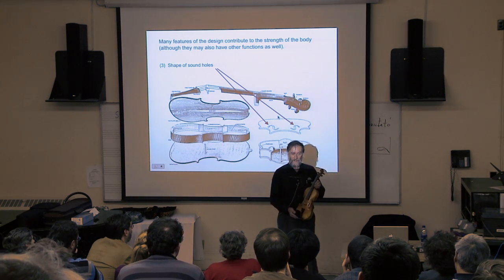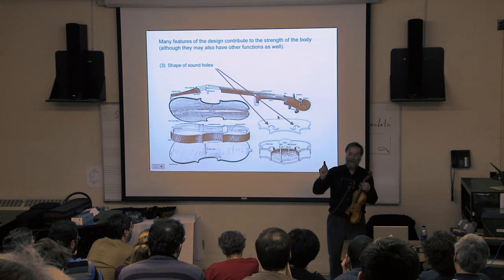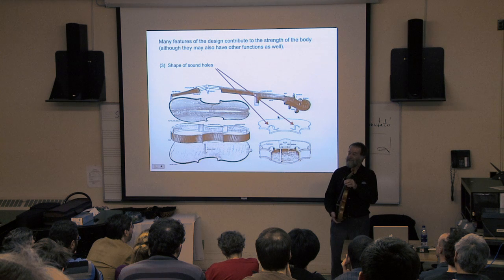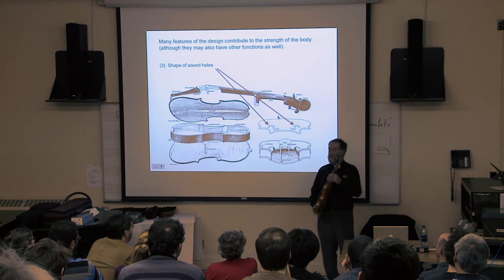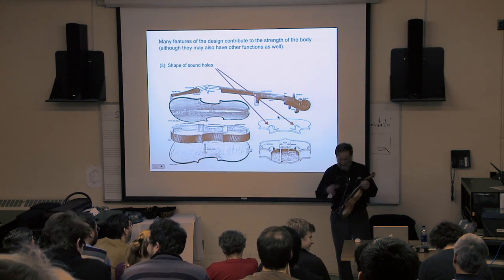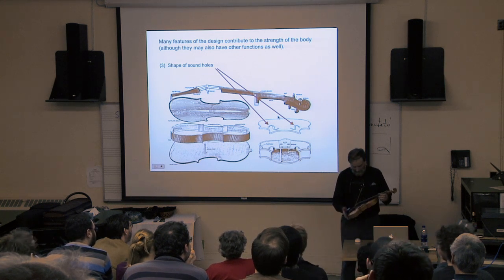That's what engineers call stress concentrations. It's the reason aeroplanes have round windows and not square ones. It's because when they built the first commercial jet liner, the Comet, they had a number of crashes because some architect type thought square windows would be nice. And they weren't a good idea because there are two cracks growing, and no one builds square windows in airplanes anymore.